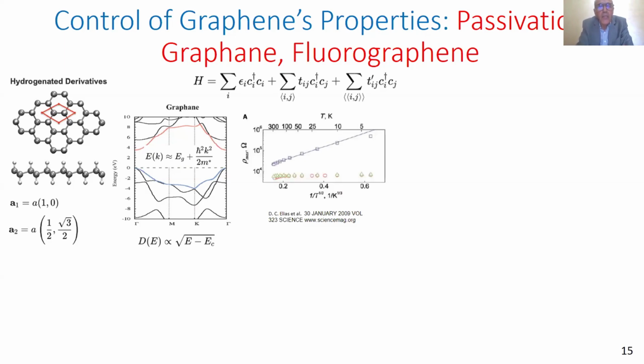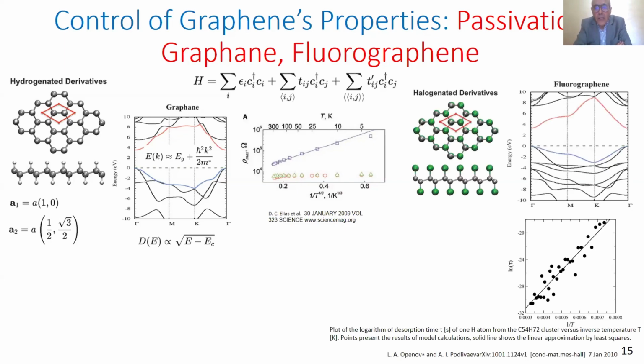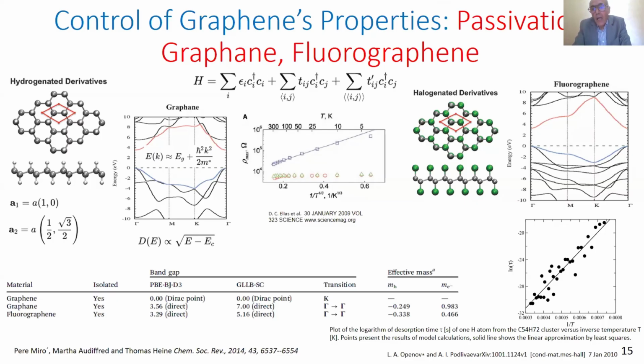And this result has also been observed experimentally by the increase of the conductivity as a function of temperature, which is characteristic of semiconductor behavior. So passivation can move graphene from semi-metal to graphane, which is a semiconductor. And the same behavior may be obtained by passivation by fluorine, which moves the graphene to fluorographene, which is also a semiconductor. And these results have also been obtained experimentally with a direct band gap.